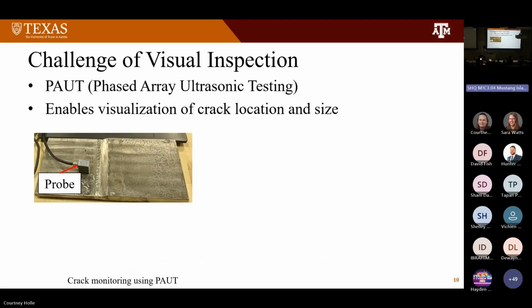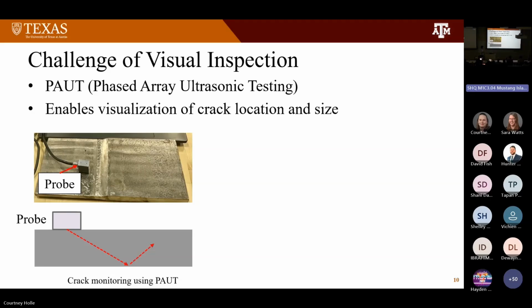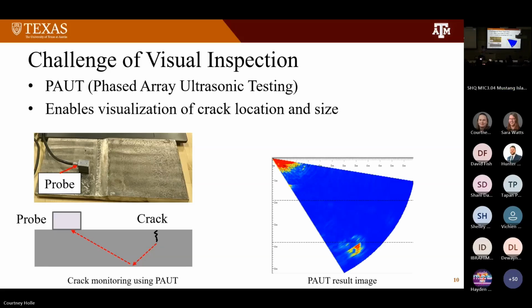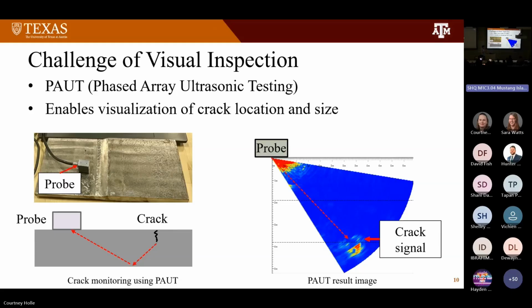In this research, we primarily use phased array ultrasonic testing, PAUT, as a non-destructive testing method. This technique uses a probe that emits ultrasonic waves. And when ultrasonic waves encounter a crack, a part of the wave will reflect back. That signal is captured and visualized. So here is an example of a PAUT result. From this image, it allows us to identify the crack location and the crack size.